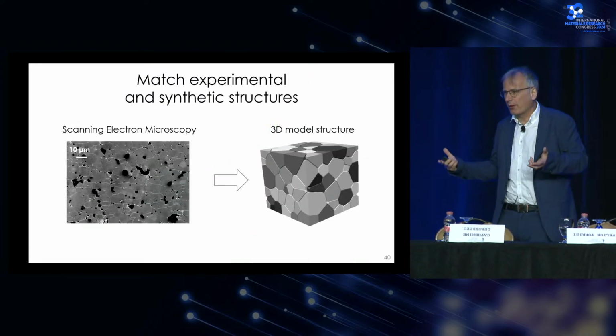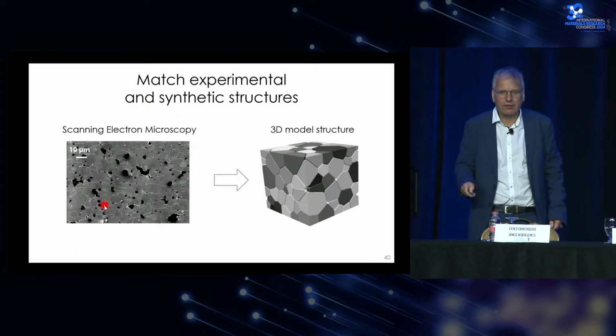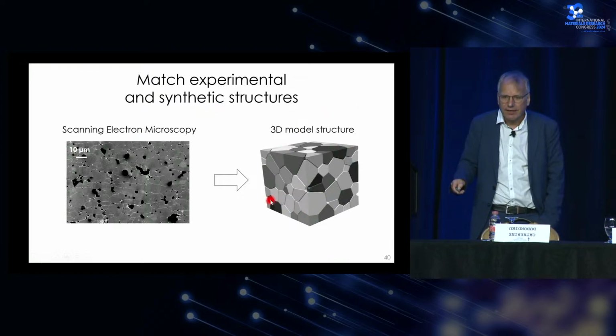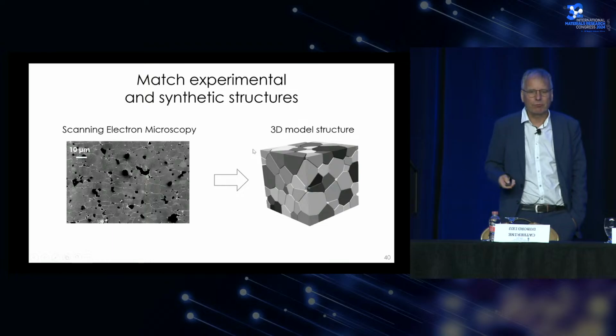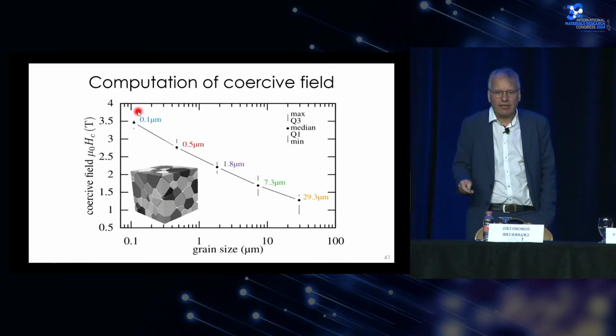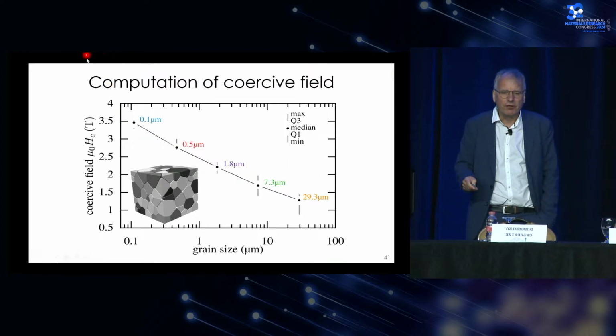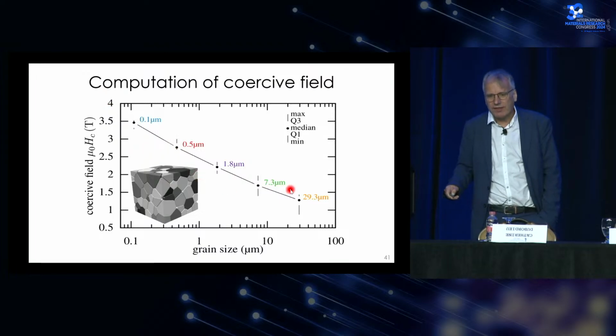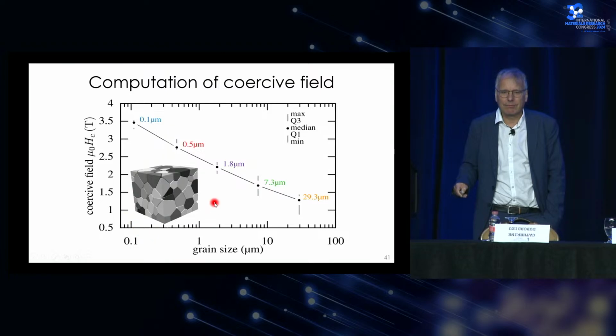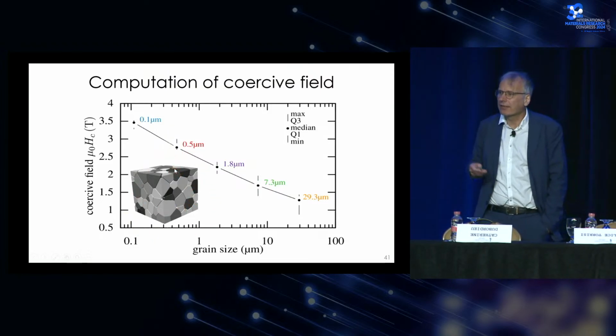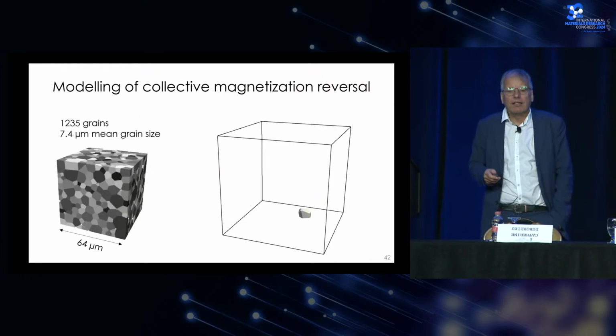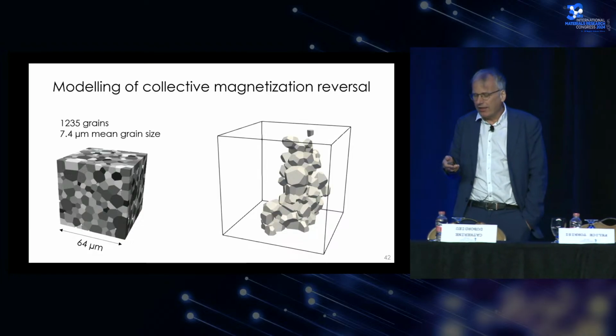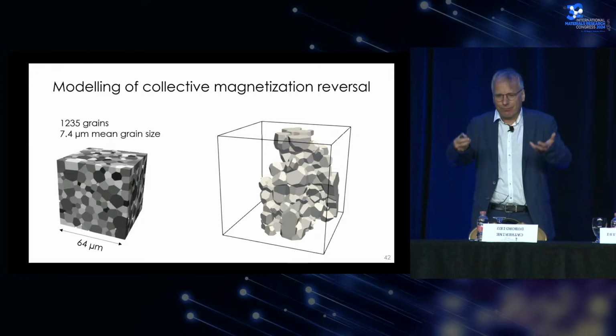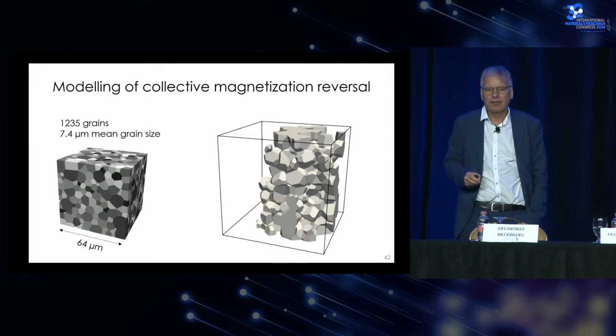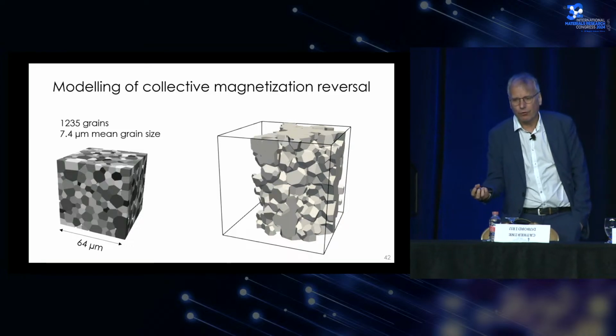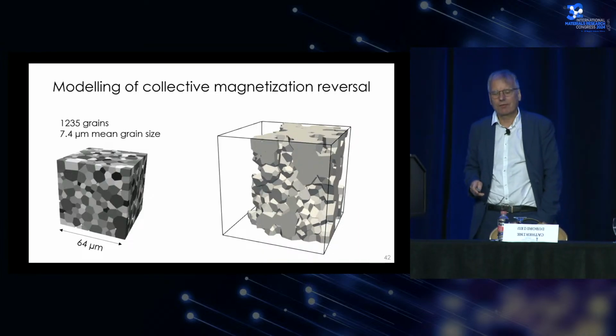Now we have to relate this to experimental data. So we have a lot of scanning electron microscopy images, and we can create equivalent 3D microstructure models. For the 3D microstructure models, we can compute the coercive field. And here, for example, you see how the coercive field changes with the grain size for microstructure models that resemble sintered neodymium iron boron magnets. We can also see how the magnetization will switch throughout the application of an external field. So if we apply an external field, we see that we form this avalanche of reversed grains in the magnet.